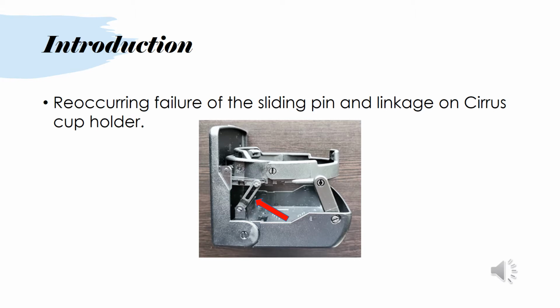I started to see a pattern with a missing linkage that is shown below with the red arrow pointing to it. Our group determined that the failure is occurring because the folding mechanism is spring-loaded. The cup holder can be forcefully opened, causing fatigue cracks on the lower pin. After being opened many times, the stress builds up in the lower pin, causing it to break off or come out of place. This results in a missing linkage and causes the cup holder to malfunction when being closed.